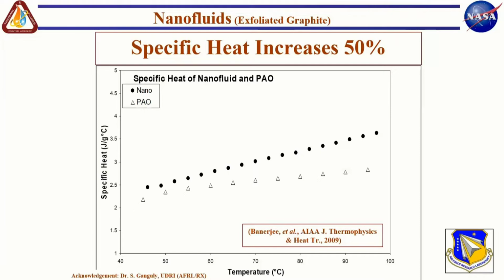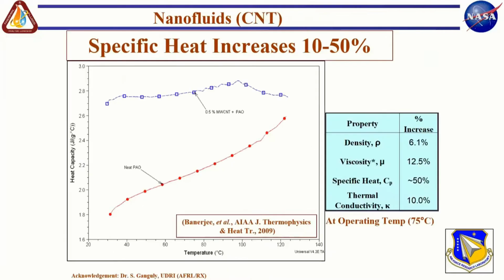And what we found was, the bottom triangles are the pure neat polyalpha olefin. And even at like 0.6% mass concentration of these exfoliated graphite nanoparticles, whose heat capacity is about 1 joule per gram Kelvin, the heat capacity increased by about 50%. And it did not make sense. And then we repeated it for carbon nanotubes. The profile of this graph was a little different, but still we got enhancement anywhere between 10 to 50%. 10% enhancement at higher temperatures, 50% enhancement at lower temperatures. So the question is, where is this enhancement coming from?